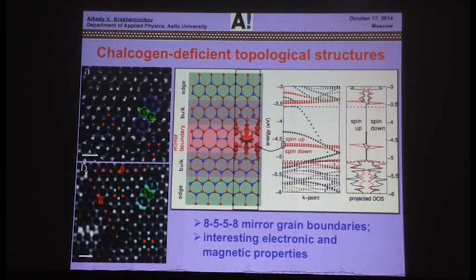You continue the process, essentially you get a grain boundary. Basically, a phase here appears with mirror symmetry, and this has a 8-5-5-8 grain boundary, which by itself is quite interesting. It's metallic and magnetic. Basically here you have a grain inside a bigger grain, and this grain was created by the electron beam here.